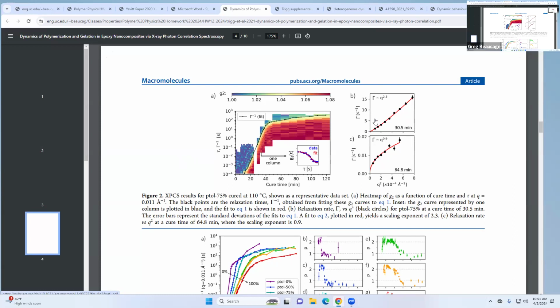Now they're plotting it against Q squared. So if I see a linear dependence between the relaxation rate and Q squared, that's diffusive dynamics, right? Now, if you look at the Q dependence out here, it's no longer at that same scaling behavior. It actually goes to Q to the 1. So they were able to identify that transition from diffusive dynamics to ballistic dynamics as a function of the curing, which is cool, right?